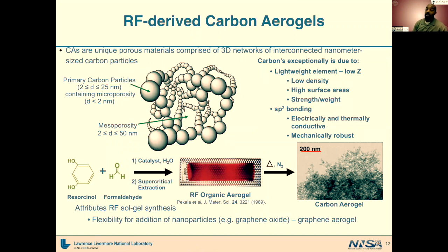How do we go about making these carbon aerogels? We use what we call a resorcinol formaldehyde derived process, or sol gel process, shown down here on the bottom. You start off with a solution of resorcinol and formaldehyde. You add in a catalyst that can be either a base catalyst or acid catalyst, depending on the final morphology that you're looking for in your aerogel. If you were using a base catalyst, you would end up with a clear, translucent, orangish wet organic gel, which when dried and then heated at over about 700-800 degrees C under nitrogen, will give you a final carbon aerogel.